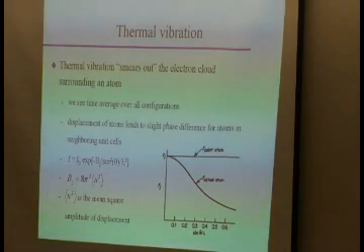Once you get into crystal structure analyses, some programs use this U, some programs use the B. There will be a big difference in numbers. As a matter of fact, a difference of 8 pi squared, that's about a factor of 70 or 80. So, somebody reports thermal parameters to you. You need to make sure that you know whether these are U or B values, because otherwise you cannot judge whether those are reasonable numbers.